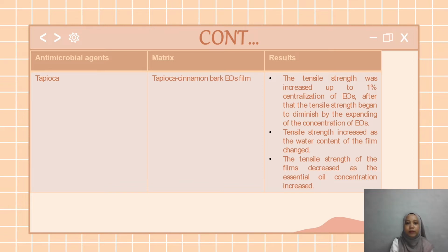The matrix is tapioca, cinnamon bark essential oils films. The tensile strength was increased up to 1% concentration of essential oils. After that, the tensile strength began to diminish with the expanding concentration of essential oils. Tensile strength increased as the water content of the film changed. The tensile strength of the films decreased as the essential oils concentration increased.